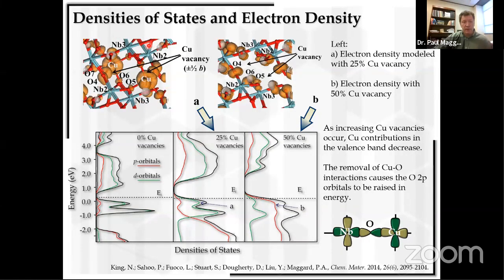in these images up here, if this copper is removed, those orbitals on copper would normally interact and push down the oxygen bonding orbitals and themselves be raised by their interaction with oxygen. And so you would have bonding and anti-bonding levels. But when that copper is removed, there's no more interaction with those oxygen p orbitals here. So as copper is removed, those p orbitals climb significantly in energy.